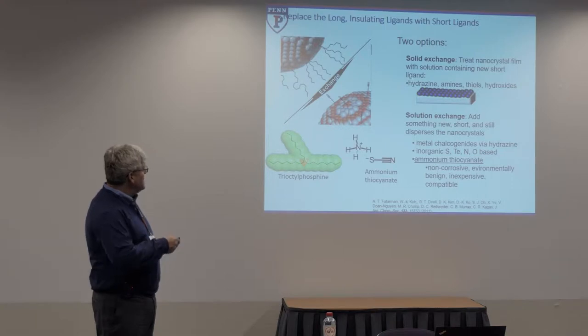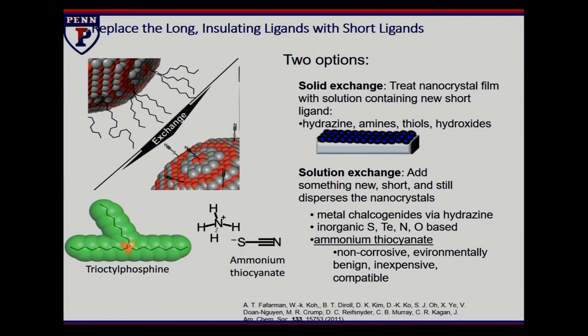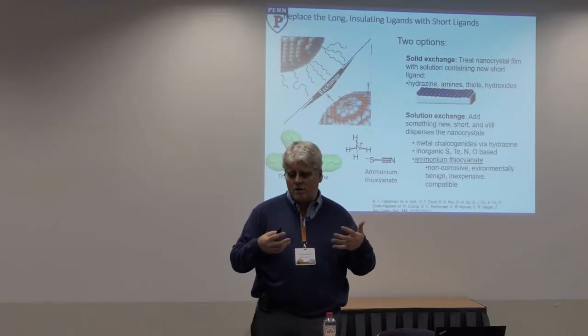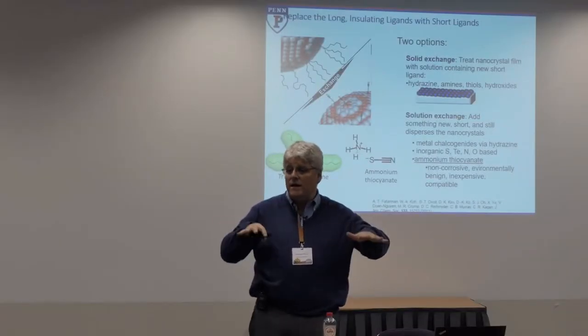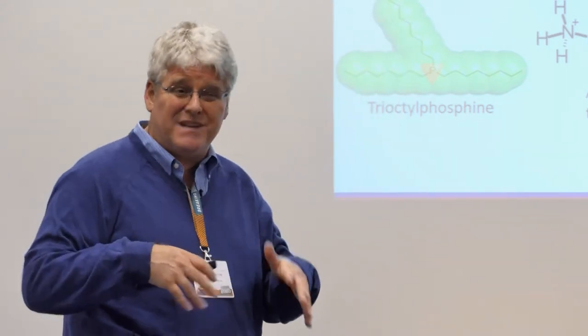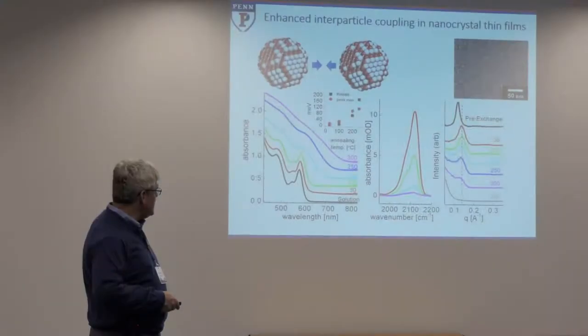And this process also had some desirable elements in that it's an exchange process that could occur in the solid state. So you could make your devices, pattern them, and organize the material, and then expose selected areas to this molecule, and it would make those materials electronically active. Any area that you did not expose to the molecule would remain insulating. So it was a way of building devices by direct patterning based on the masking and the deposition of the ligand. Not that that's a terribly practical thing, but it allows you to begin developing strategies for making different types of devices.